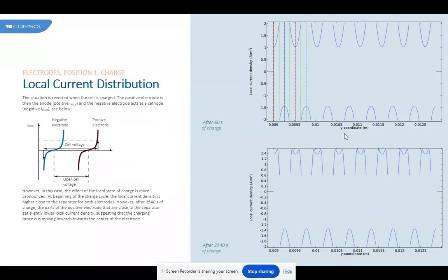Local current distribution, electrodes position 1, charge. The situation is reversed when the cell is charged. The positive electrode is then the anode, positive, and the negative electrode acts as a cathode, negative I local. However, in this case, the effect of the local state of charge is more pronounced at the beginning of the charge cycle. The local current density is higher close to the separator for both electrodes.